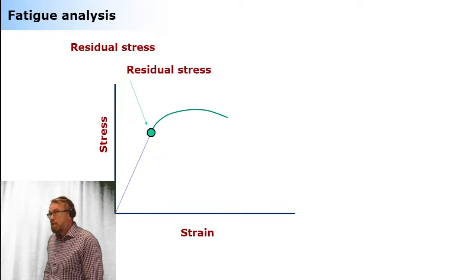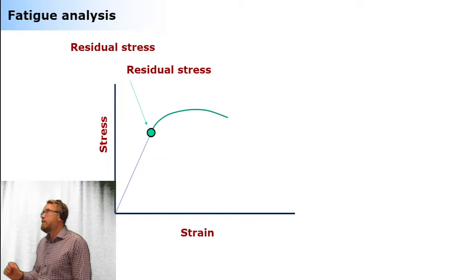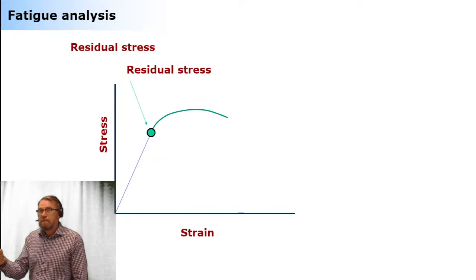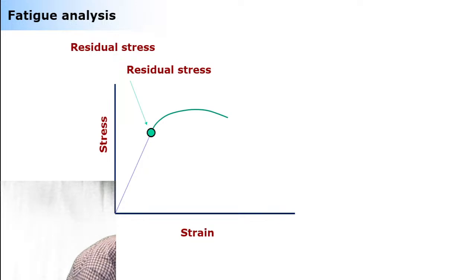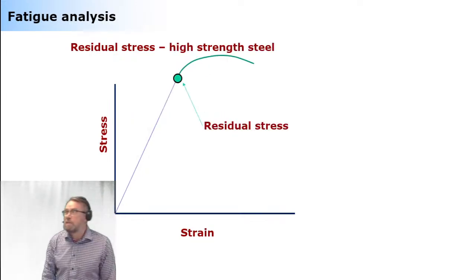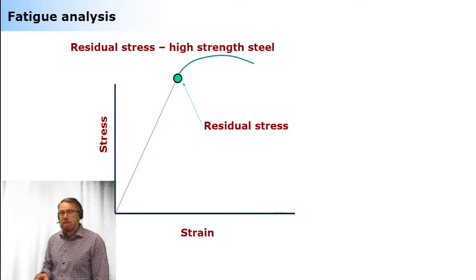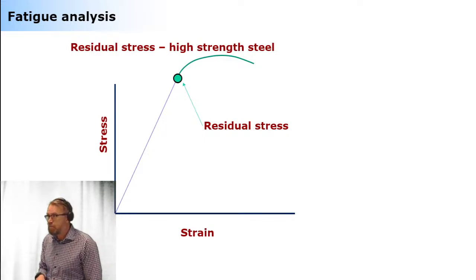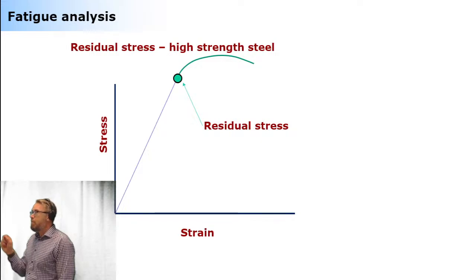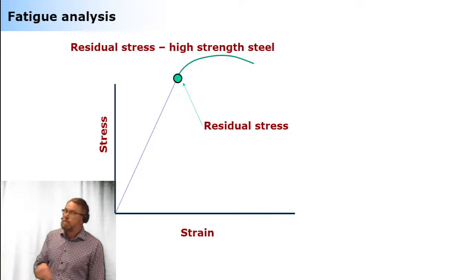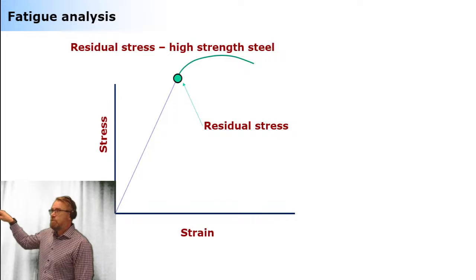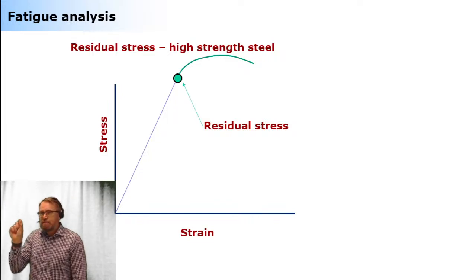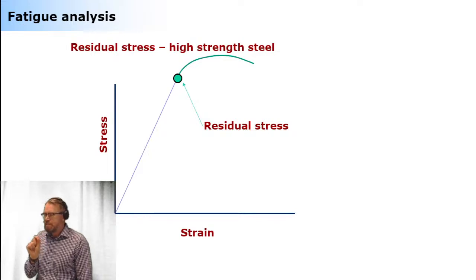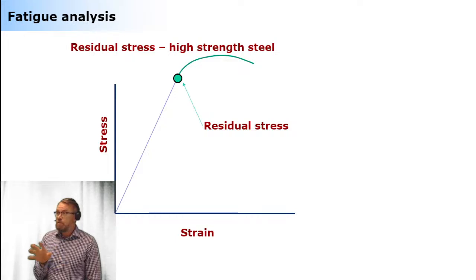How much is it going to help if you change your structure to be built using, let's say, ultra high strength steel? It helps nothing. And why? Because what happens is this: you just have this linear line longer compared to the conventional steel. But that doesn't help you because the residual stress, again, because of the violent way you introduce the heat to your structure, is going to be again in a corner where the linear turns out to be nonlinear. Again, let me emphasize, very locally. You don't see this when you look at the entire structural behavior, but you see it when you look locally. This is a big problem when you're using high strength steel.